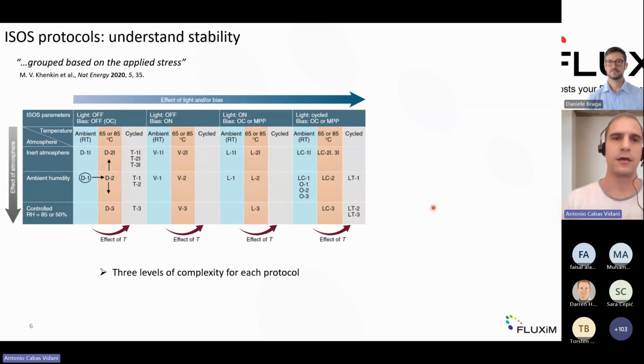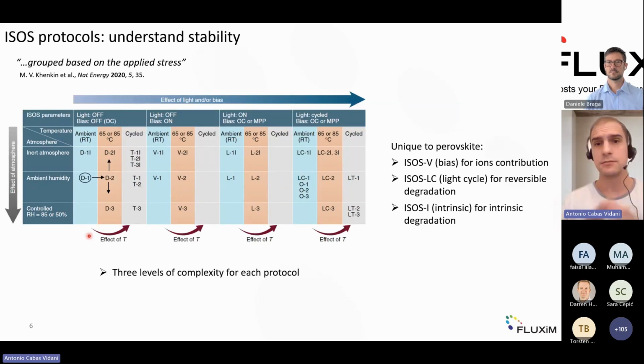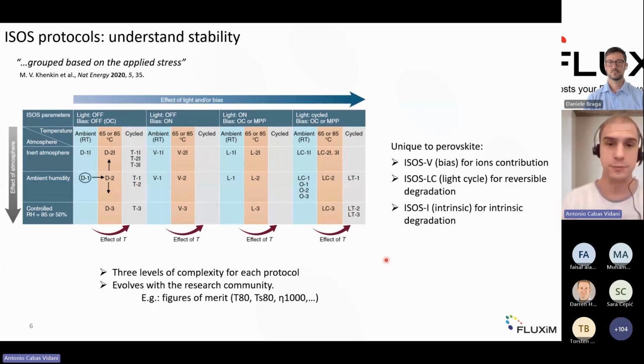And from there you can again vary and maybe get rid of the atmosphere. So you get D2I, you see here on the top. Or you increase the humidity, for instance, for additional stress. On top of that, it also provides protocols that are specific to perovskite. And they're specific in the sense that they aim at conditioning or studying the perovskite for its ions contribution to the stability, or to study the reversible degradation that we just mentioned, as well as intrinsic degradation that I just indicated with a protocol.